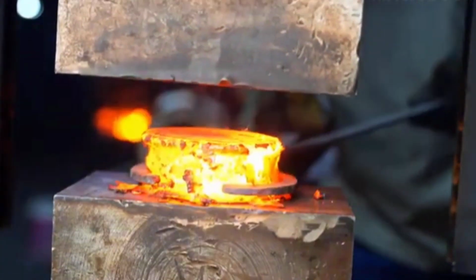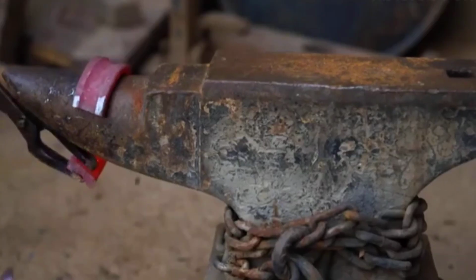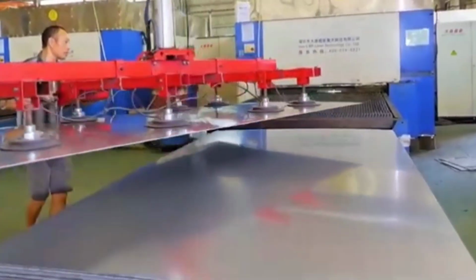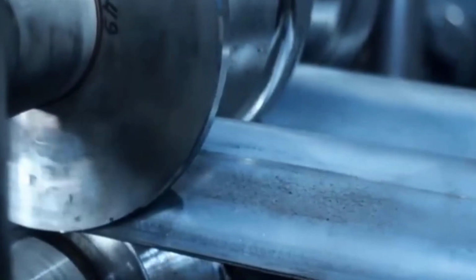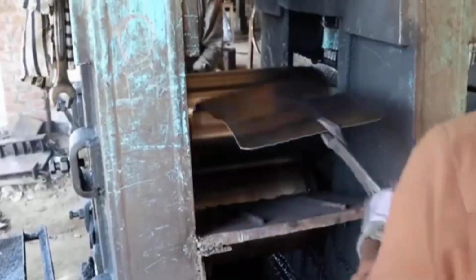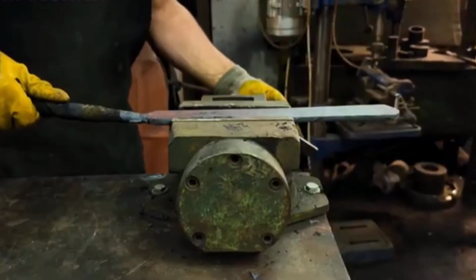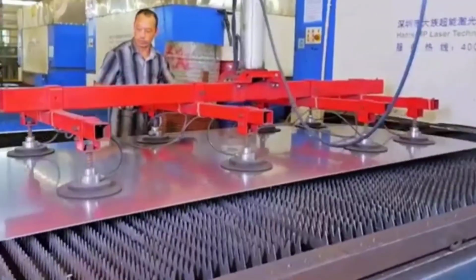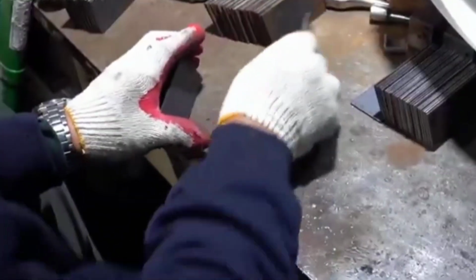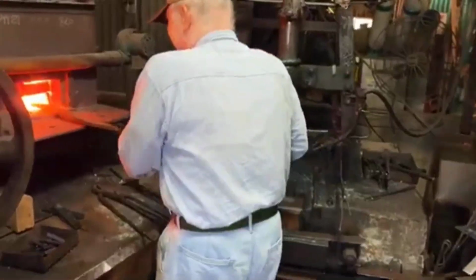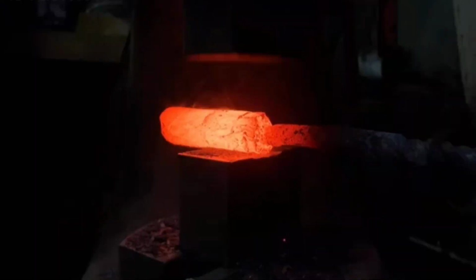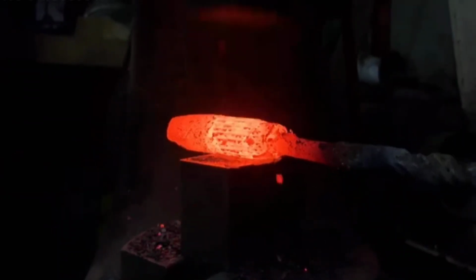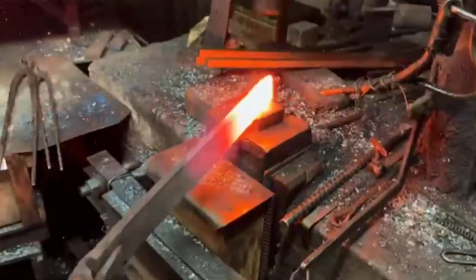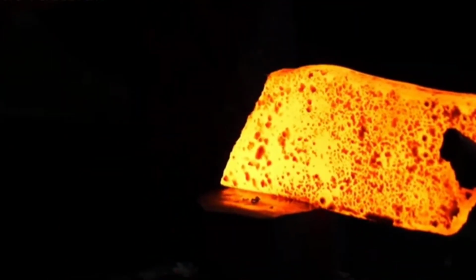Depending on the design specifications of each knife line, the steel sheets are trimmed using mechanical shears, CNC cutters, plasma, or laser machines. The result is a series of rectangular or wide strip billets, typically between 2 and 6 millimeters thick. Even though it's a transitional stage, this is one of the most error-sensitive steps in the entire process. A single crack during rolling or a cutting deviation of just a few millimeters can render an entire billet unusable. But those that pass inspection are now ready to begin their transformation into fully forged knife blades.